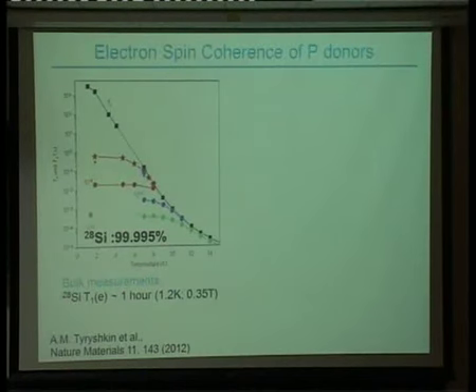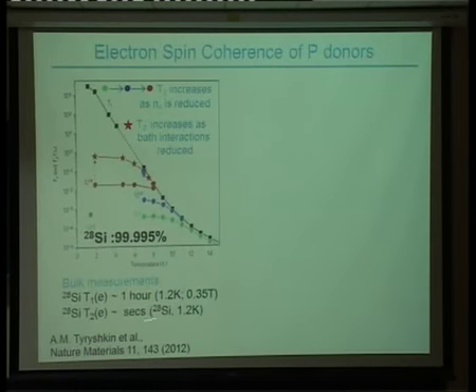One of the last reasons to motivate why you would want to look at phosphorus donors in silicon is to look at the T1 times. Here you can see the T1 times go up to 10 to the 3 seconds. These are the T2 times here, as a function of carrier density. This is all done in isotopically pure bulk measurements. You can see that as you reduce the carrier density of these systems, you get larger and larger T2 times. And if you do a modified Hahn echo sequence, you can push that even further, so you can get T2 times of seconds in the silicon system.